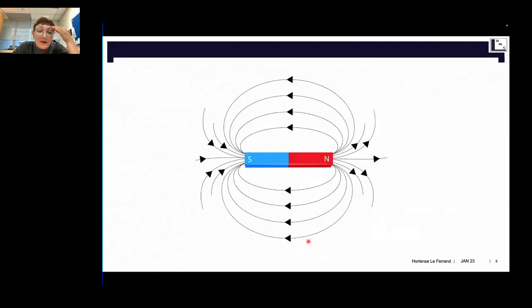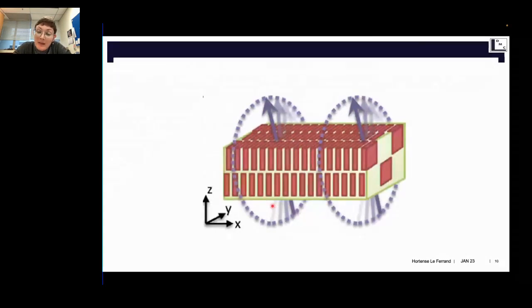Throughout this talk, I will talk about magnetic fields from magnets as the tool we use to create this bio-inspired microstructure. So we use an external magnetic field, and more specifically, a rotating magnetic field. In this picture, the rectangle in the middle would be the material. The red would be particles that have some properties, and the green would be a matrix. And they are assembled, as you can see here, in a very well-ordered structure, a little bit like the nacre, but in another direction, like a vertical nacre. And this was done using a rotating magnetic field, which is symbolized with these circles. Okay, so rotating magnetic fields is what we're going to use to build these microstructures.